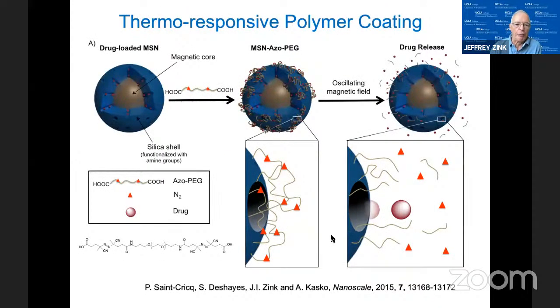A second type of thermoresponsive coating, and this for the first time now involves a polymer, is we use the polymer shown on the bottom left there, which has these azo bonds. This molecule is used when you heat it up to make radicals. It's a radical initiator for polymerization. In our case, we just wanted to look at the bond breaking as the nitrogen gas comes off and the whole polymer breaks up. So we attach both ends of this polymer all over the place on the surface of the particles. It's everywhere. It makes a big mess of polymers on the surface.